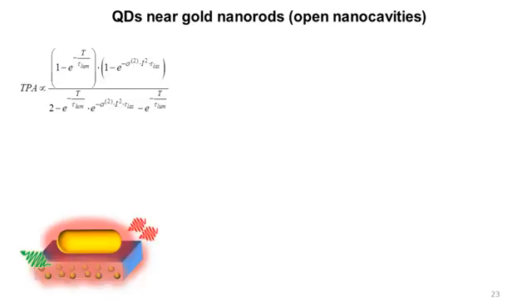The alternative approach for increasing the two-photon-excited photoluminescence is to increase the two-photon absorption probability. Two-photon absorption cross-section is the main parameter that reflects the two-photon absorption efficiency, regardless of the amplitude of the excitation field. Previously, we have shown that the photoluminescence saturation measurements allow finding the two-photon absorption cross-sections of quantum dots in the ensembles without prior knowledge of particle concentration and quantum yield. To describe the saturation, we use the equation that expresses this process as a function of the excitation intensity.